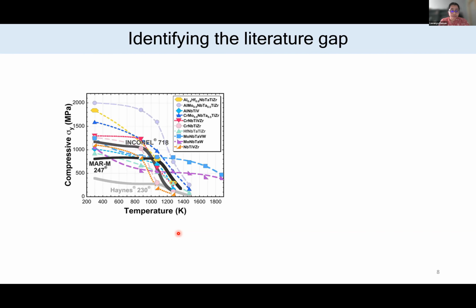So before going into that, I've tried to have one slide which will help us understand the gap in the literature. If we focus on this figure, it shows the variation of compressive yield strength across different temperature scales for different materials. This has mostly different refractory HEAs. They have also shown superalloys like Inconel, Haynes, and MAR-M 247. So at first glance, one may think that these superalloys drastically reduce their strength as we go to temperatures above 1000.